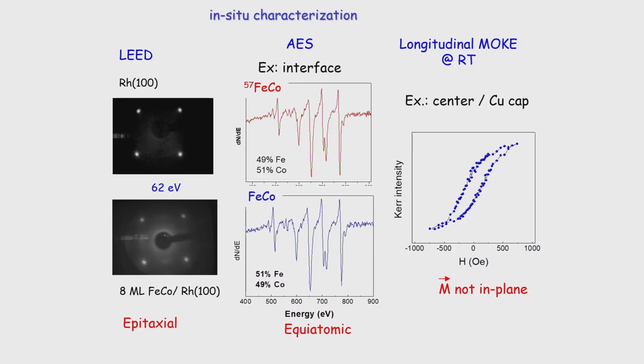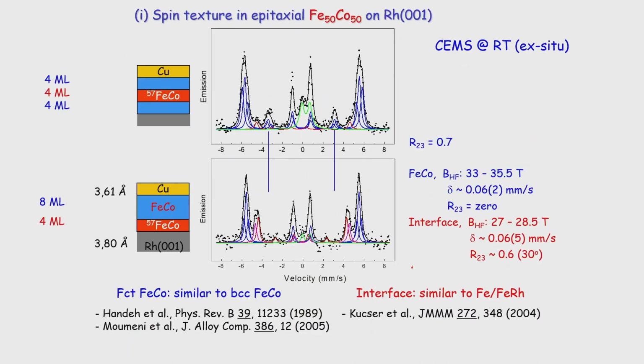Of course, doing it by MBE, you have to know that you have really good epitaxial growth, that the composition is really equiatomic, by doing, for example, Auger spectroscopy in situ. And then you do MOKE in situ, you see that the longitudinal MOKE loop is not square. That means the moments are not in plane, it's out of plane, or there is some perpendicular anisotropy. And then we did the CEMS, okay?